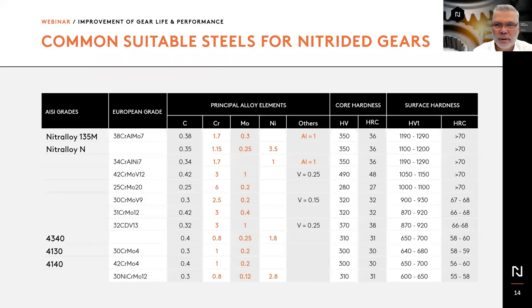Now, nitralloys have been developed almost 100 years ago, probably in the late 1920s, as a fruit of research into nitriding. Of course, nitriding controls were nowhere near where they stand today, and those components had to be machined after nitriding, because the process control was not very good. However, major steel makers such as Krupp in Germany have come up with formulations that, among others, have alloying elements such as aluminum that allow them to obtain extremely hard components and very high quality gears.